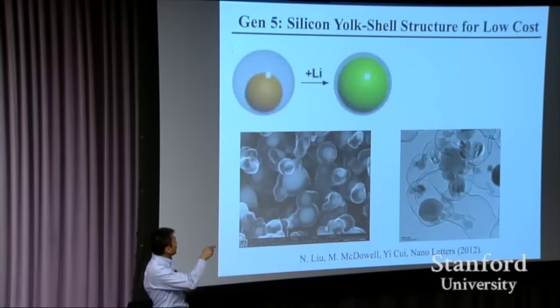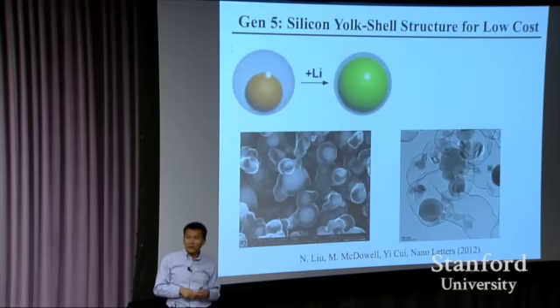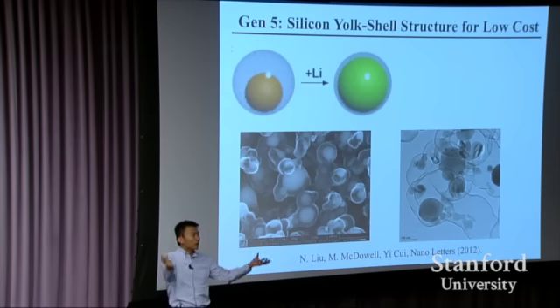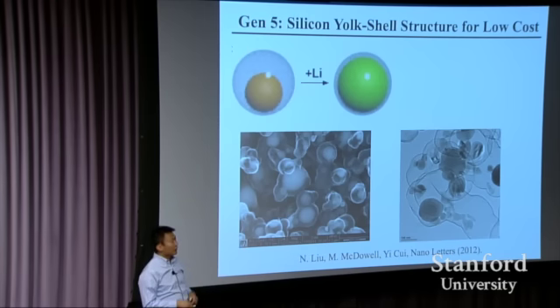Now you can make almost anything, any shape, any combination you like through smart synthesis. You can engineer empty space right here, exactly right. Lithium comes in, silicon expands, it just exactly fits without cracking your coating. And then the electrolyte is sitting outside, so it doesn't see what's going on inside. This is the yolk shell structure, a silicon nanoparticle with a carbon shell.